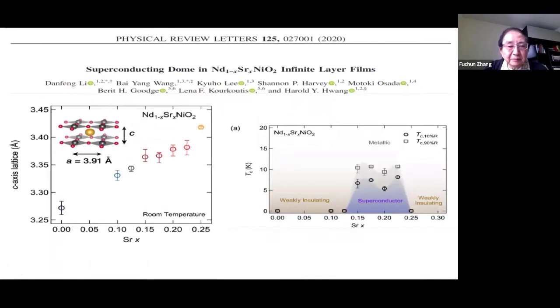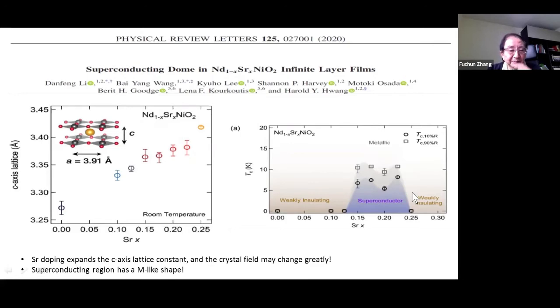The other experiment shows that the lattice constant along the z direction is changed after doping. And they plot superconductivity as a function of the strontium doping. This is M shaped, up and down and up like this. So these are some of the phenomenology.